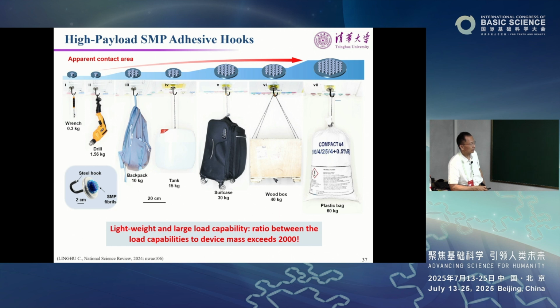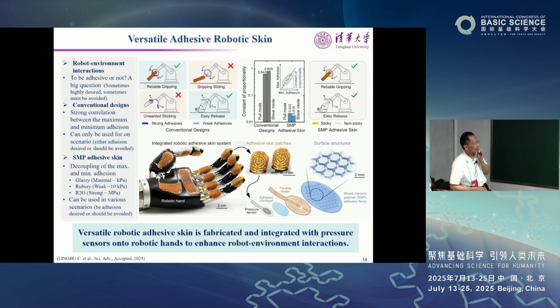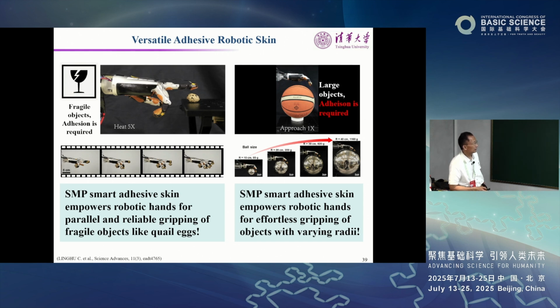And now you can test. You can actually pick up very heavy goods, up to 60 kilograms, easily achieving tens of kilograms of weight, and it's fully reversible. This is the amazing part of this design. And so we designed a versatile adhesive robotic skin that can have interactions. We can have three kinds of states. One is glassy, with minimal, very weak adhesion. Almost you cannot feel it. Rubbery adhesion is pretty weak, and phase transition adhesion is very strong. You can develop some kind of robotic skin that interacts with the environment with three states: no adhesion, weak adhesion, strong adhesion. And this can pick up very delicate, fragile objects, as well as large objects.